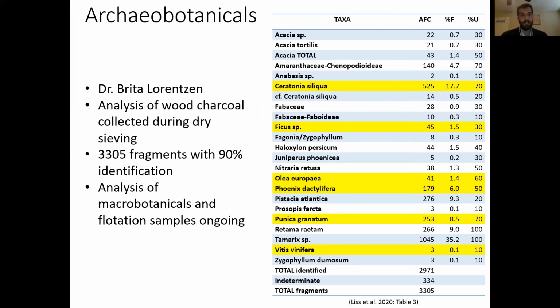This study was largely done by Dr. Britta Lorentzen. She analyzed the wood charcoal that was collected during dry sieving in the field. She analyzed over 3,300 fragments, 90% of which were identified. This analysis is ongoing, and a larger study is in the works based on the macrobotanicals and the flotation samples. The chart on the right side shows the results of this first preliminary study.